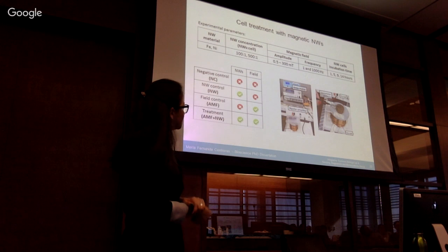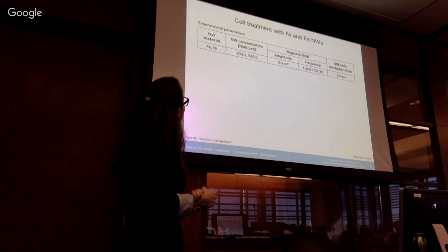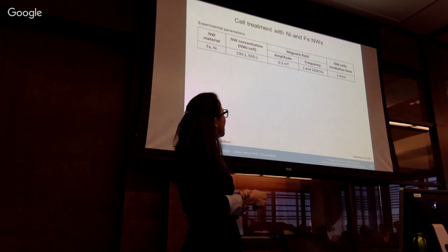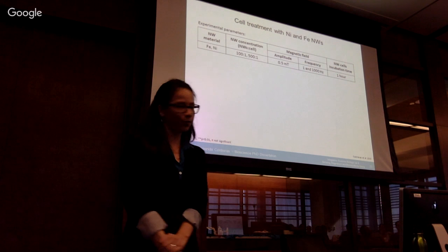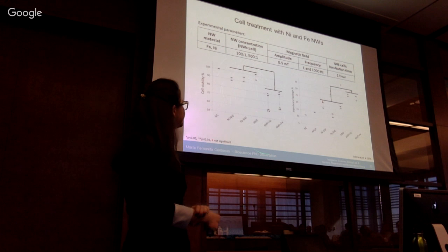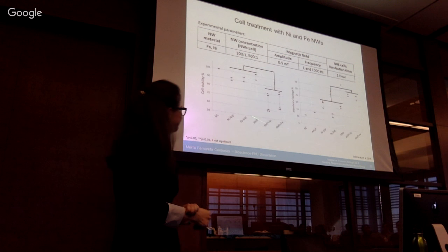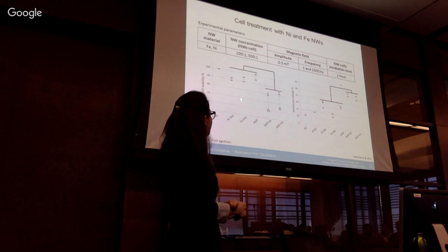Okay, for the first set of experiments, I used the two materials, the two concentrations, the lowest amplitude, and the two different frequencies, 1 and 1,000 hertz, and I incubated the cells with the wires for 1 hour. These are the results for cell viability. These are the results for cell membrane leakage. And in the bottom axis, you can see the different conditions. So the negative control, only nickel wires, only iron wires, only field, and the combination. And the same here for LDH.